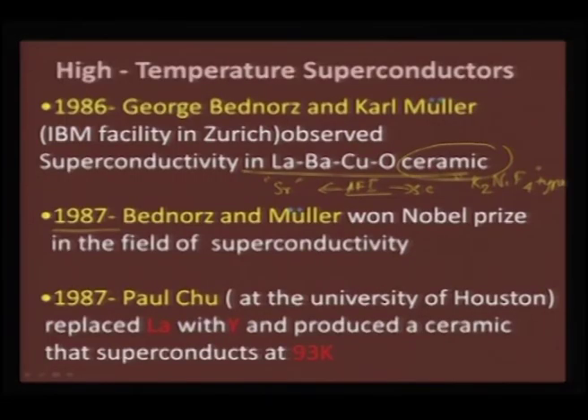Nevertheless, the excitement that was generated led Paul Chu and his co-workers at the University of Houston to replace some of the lanthanum with yttrium, and then they produced another ceramic that superconducts at 93 Kelvin instead of the one which shows it at 34 Kelvin. So, this was a quantum jump when this discovery was made.